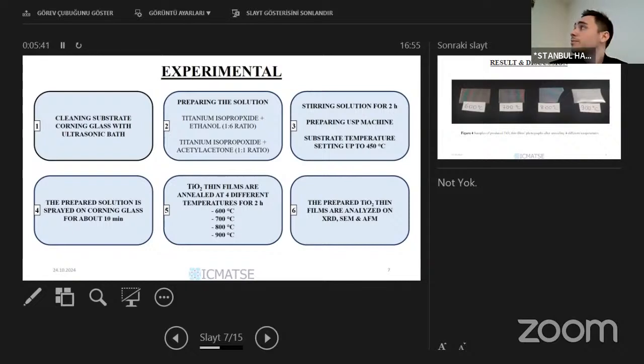There are three chemicals: titanium isopropoxide, ethanol, and acetylacetone. Titanium isopropoxide and ethanol are mixed in a 1:6 ratio by volume, and titanium isopropoxide and acetylacetone in a 1:1 ratio. We use that solution, and after preparing it,